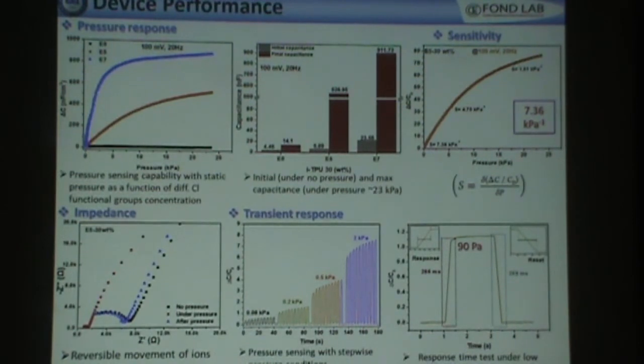And as I mentioned earlier on, you can see that at initial state, we have a lower initial capacitance value, and then at maximum pressure, the final capacitance value also increases. This change in capacitance ensures that we have a higher sensitivity, which is quite good for any device fabrication. We can also see from the impedance spectroscopy that our system has a reversible ion movement. This is also very good for the device stability.